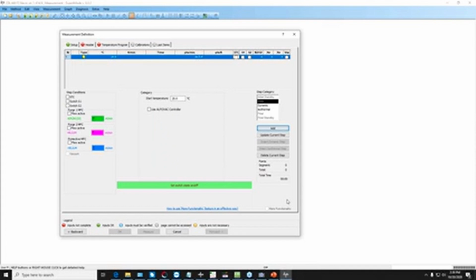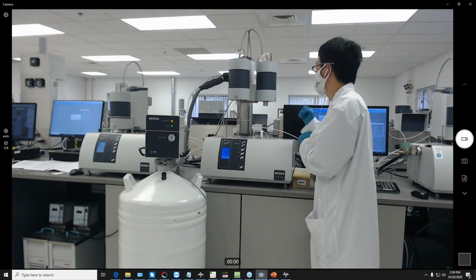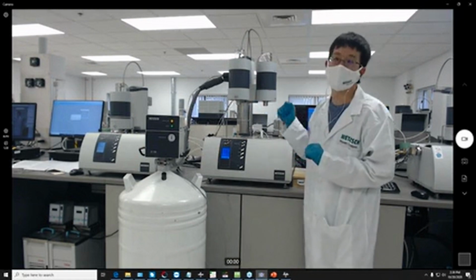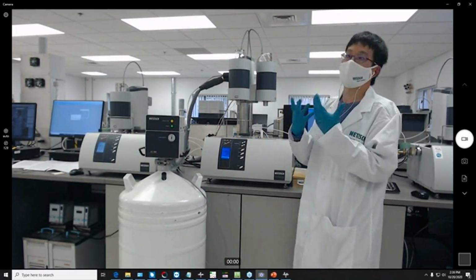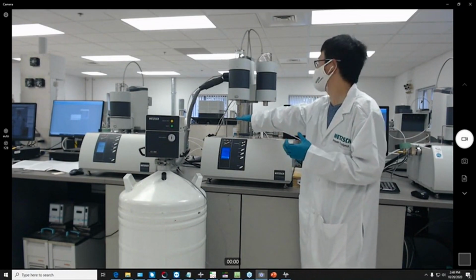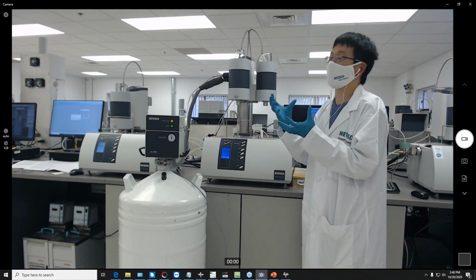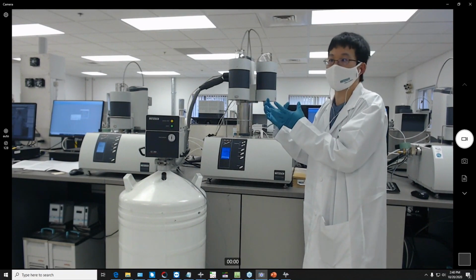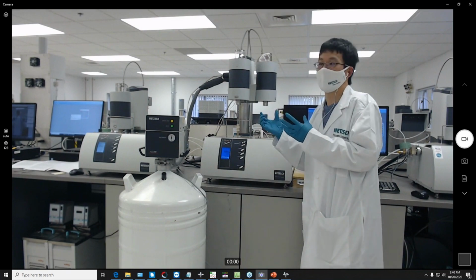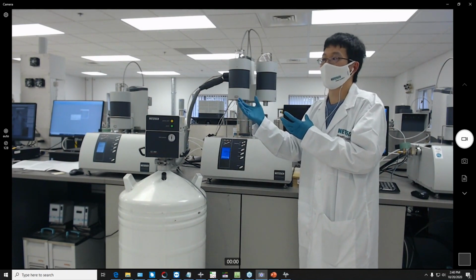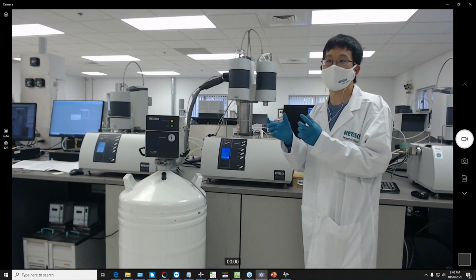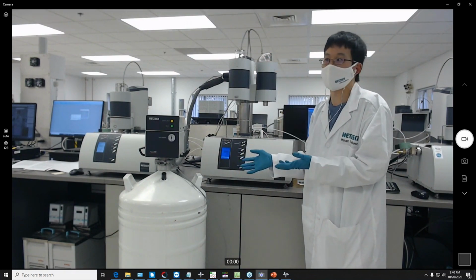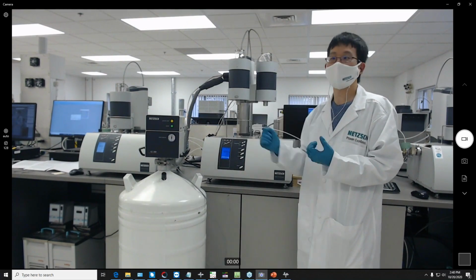Is it normal for the DSC signal to go steadily downwards with increasing temperature, linear heating? It is not surprising if you see that. The DSC signal is measuring the heat flow differences between your reference crucible, which is in the back, and your sample that's in the front. In an ideal perfect situation, your sample carrier would be sitting in the center of your furnace, and your heating elements would uniformly heat both the reference and the sample crucible, but likely that's not going to happen. Your reference crucible might sit slightly closer to the wall of the furnace or vice versa, and that's where you might see some of those drifts, either upwards or downwards. If it was ideally perfect, it would be perfectly flat, but we usually don't see it.